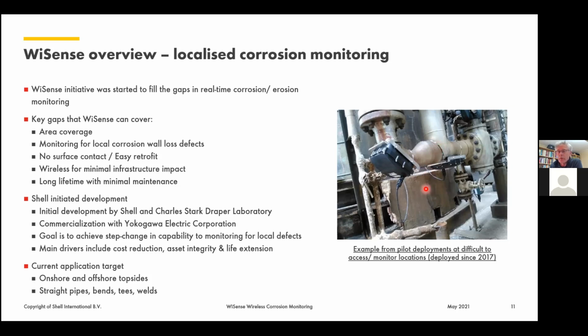So what you can recognize in this picture is that the sensor, the dark body, is mounted in a frame, and what is not so well visible is that the frame is attached to the pipe, and you can see it here with a strap and with a strap over there. We have different kinds of attachments around the pipe in use nowadays, and it means also that the patches can be taken out of the frame. For instance, if you want to do confirmation measurements with ultrasonics, or by taking a radiograph. You can also shoot with a radiograph through the patch, but then you get a bit more clutter in the radiograph. But removing it, keeping the frame in place, and replacing the WiSense patch is a procedure that works, and that's a very strong point for the technique.